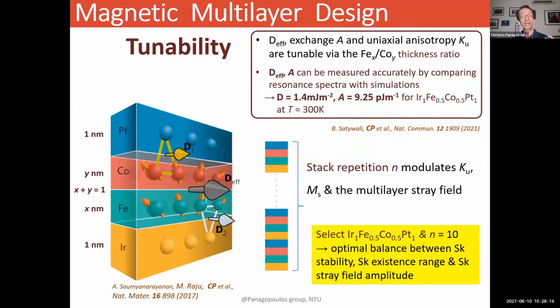Also, you can have more tunability by changing the stack repetition, that is N. And this modulates again the uniaxial anisotropy and the saturation magnetization of your multilayer. So going through many materials and many trials, we were able to select this particular sample for the discussion with the superconductor that I will continue from now on. So we select iridium 1, iron 0.5, cobalt 0.5, platinum 1, and we have 10 repeats. And this gives us the optimal balance between the skyrmion stability, the skyrmion presence range, and the skyrmion stray field amplitude, which we need if we are to couple or induce superconducting vortices.